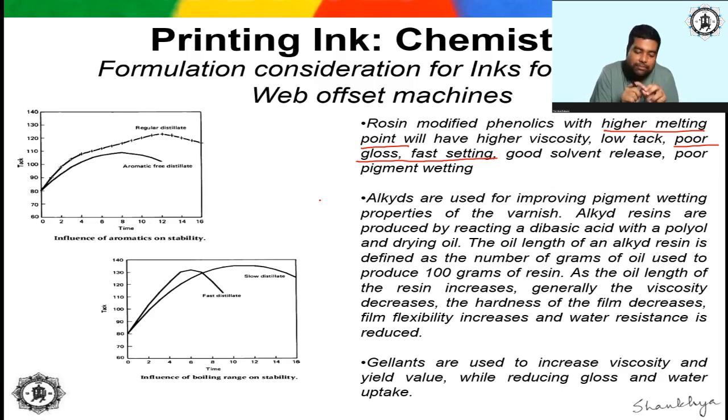such that all the peaks and valleys of the paper are out of view. That means a uniform layer of that high viscosity component of the ink will cover the peaks and valleys, and there will be regular reflection, or what we call specular reflection, giving a very glossy appearance.